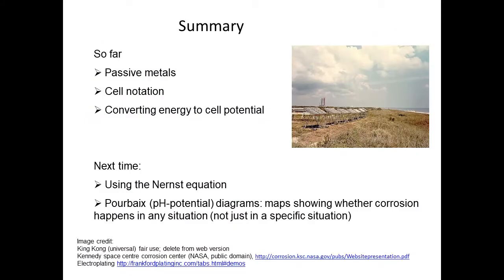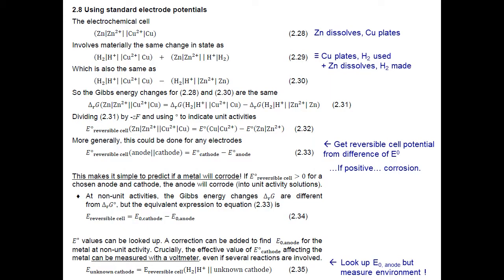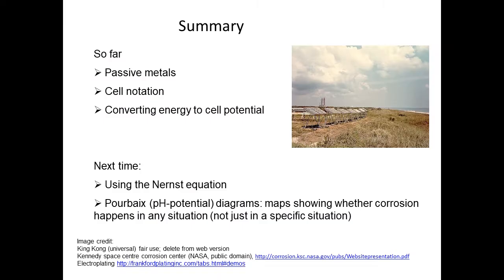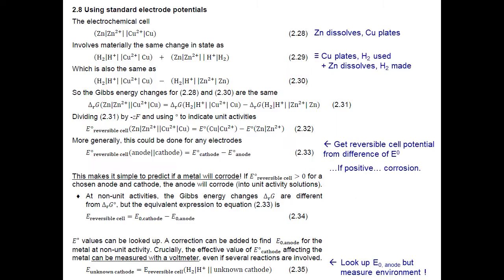Please do be aware it's very important because it allows us to make a calculation as to whether any metal corrodes, dissolves, say, and all we need to do is look up one number, the standard electrode potential for the metal. We maybe need to calculate a correction to its equilibrium potential if it's at non-standard concentration. And we need to do one measurement representing the average effect of all the oxidizing agents in the environment. So this means that we succeed in what we wanted to do. We have a simple method for working out whether corrosion happens.